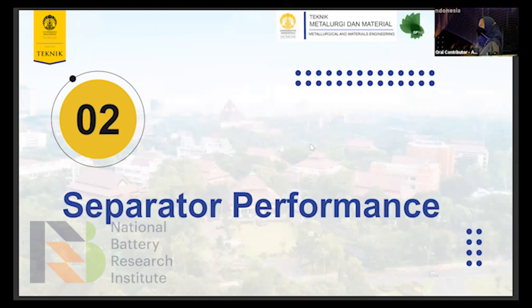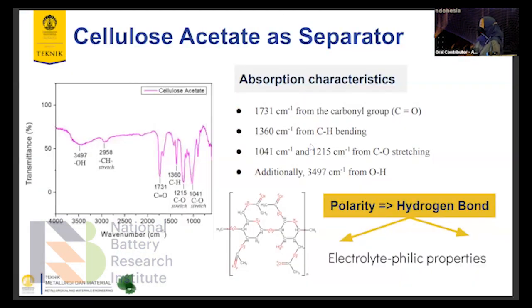From our research, we also observe and analyze its performance. First, we need to validate the cellulose acetate as separator. Cellulose acetate has a few absorption characteristics, such as carbonyl group, methylene bending, C-O bond stretching, and O-H bond absorption. The thing that we have to note is cellulose acetate has polarity because of its polar groups such as carbonyl group and hydroxyl group. So it can form a hydrogen bond. This hydrogen bond will influence the cellulose acetate performance on its hydrophilicity and electrolyte-philic properties, so it can be wetted more easily.